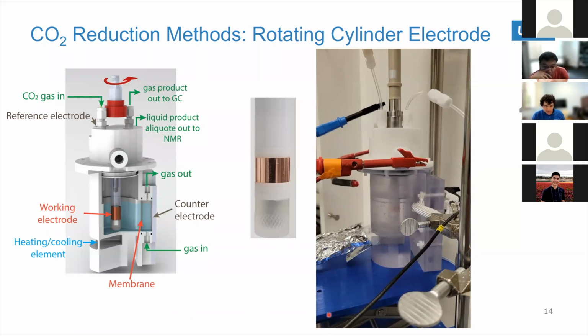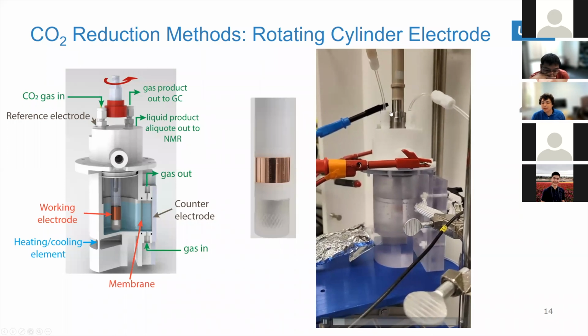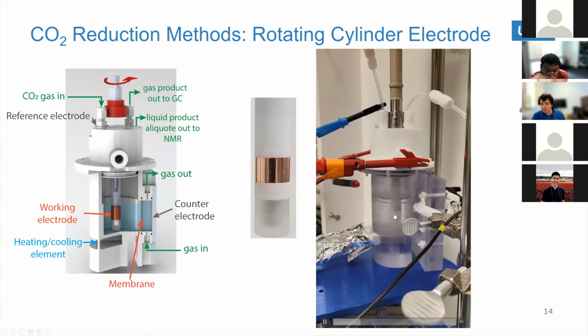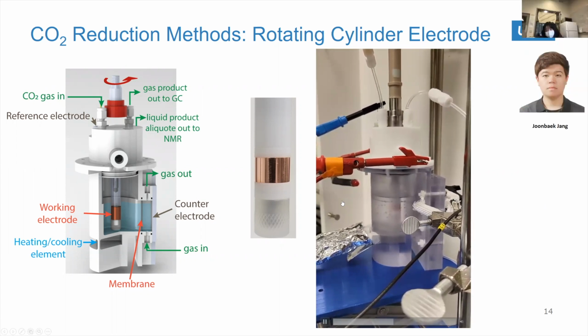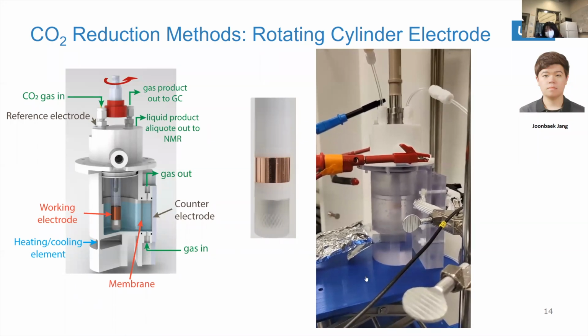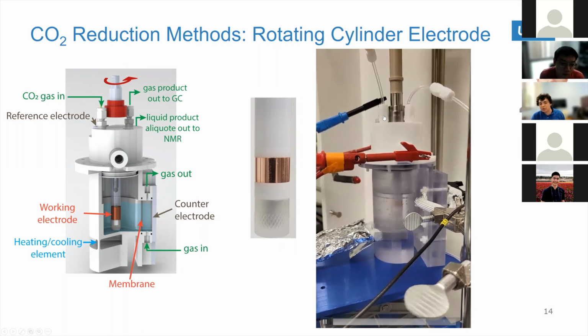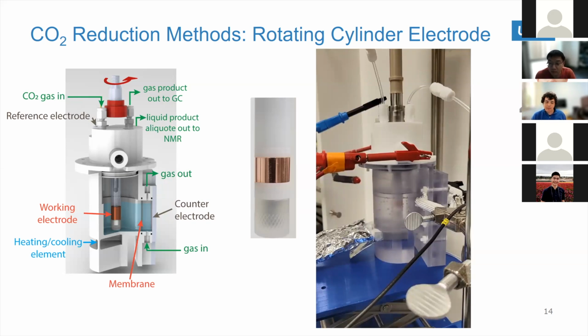Let me see if I can play this video. Here you can see that we're changing the rotation. As we change the rotation of the magnet, the electrode also changes in rotation, and we can slow it down or increase it. So we can also look at the system under dynamic conditions of changes in mass transport. In this cell, we have bubbling of the gas in the electrolyte. We also have the gas that is coming in and the gas that is going out towards the GC. So again, we can measure the same catalyst under different conditions of hydrodynamics, different pH if we want. We can change the electrolyte, the temperature, and also the pressure within a small range that can be tolerated by these cells. We're building a cell for high temperature and high pressures, in the order of 100 bars, to do the same type of electrochemistry.